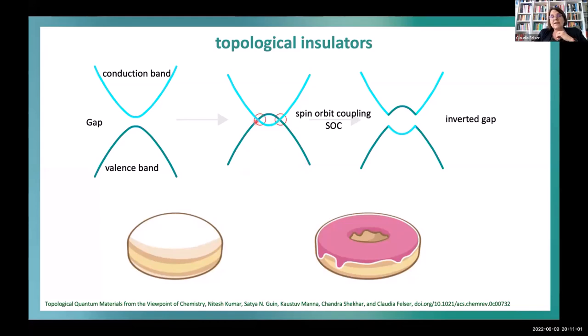So we have these crossing points, and this is even a general statement, has nothing to do with topology. Depending on the symmetry of the crossing bands, we can have this forbidden crossing and open up a band gap. But if you have heavy elements, spin-orbit coupling might play a role, and then we open up a band gap and get a part of the valence band in the conduction band and vice versa. So if we symbolize this by geometry, this would be symbolized by a trivial topology, a pancake, while this electronic structure will be symbolized by a donut.